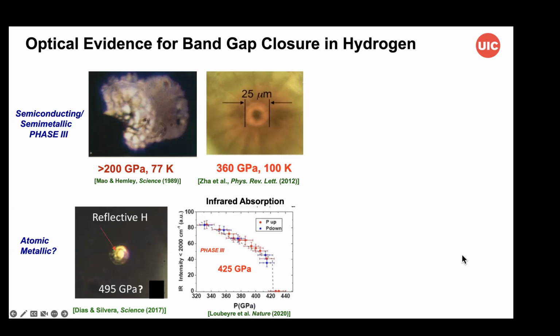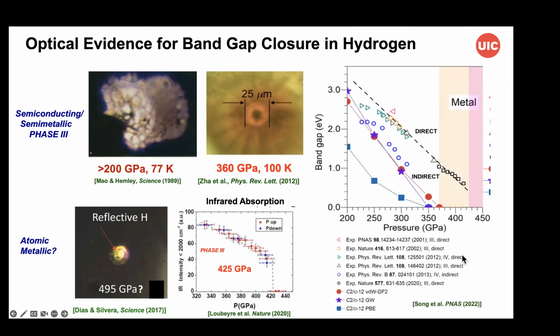The group of Paul Loubeyre found evidence for actual closure of the gap at higher pressures than we reached in our earlier studies. And this is also complemented by electroconductivity measurements by Mikhail Eremets' group. So we have now this interesting plot of band gap closure as a function of pressure, theoretical calculations, as well as all the available experimental data from optical measurements, showing really some degree of convergence, the possibility of a semi-metallic phase before becoming fully metallic in an atomic phase. There are controversies as to whether or not there are intermediate phases, whether there is a phase field of stability of the semi-metallic phase, but there is some degree of convergence now between theory and experiment and among theoretical groups for the behavior of pure hydrogen under pressure.